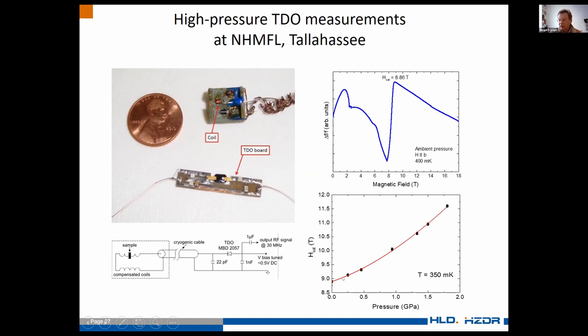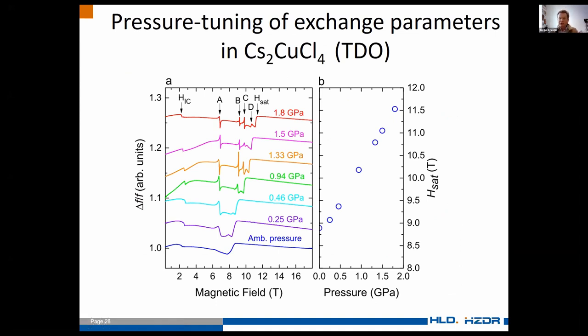We did these measurements as a function of pressure, and we were able to see how the saturation depends on magnetic field. You can see we can build this saturation. What is interesting is that when we apply pressure, we observe a number of transitions. So by pressure we are able not only to change the saturation field, but some additional transition appears. We can only speculate about the exact nature of this transition.